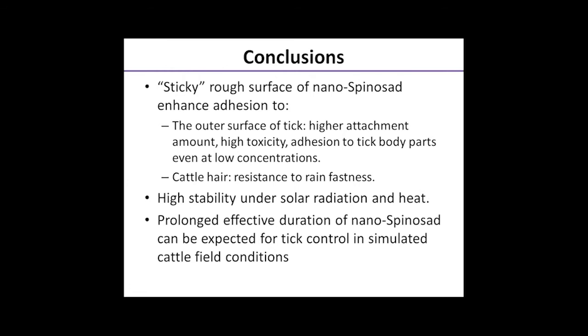The adhesion performance was further quantitatively measured using rainfastness test. Moreover, solar radiation tests revealed that the nanospinosad exhibits more than 10 times higher photostability over the commercial product. This work paves the way towards development of high-performance nanobiopesticide for sustainable agriculture and applications.